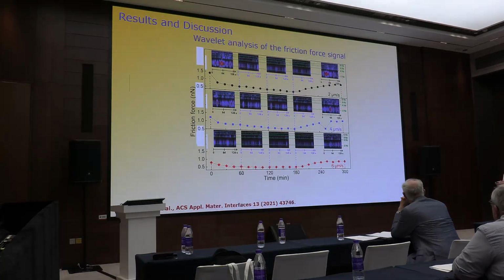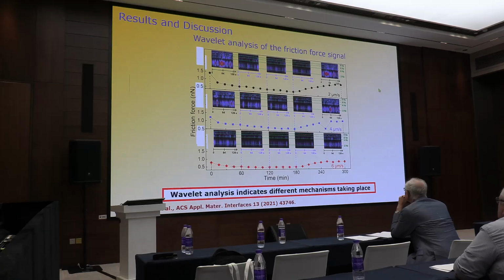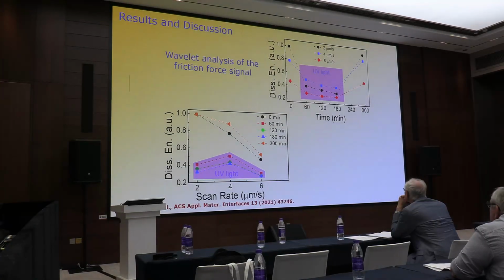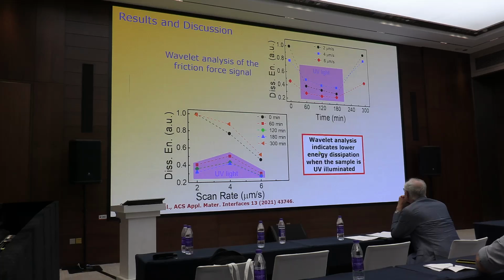Well, this is analysis of the AFM data. This is wavelet analysis developed by one colleague who analyzed the friction force. And what does it mean? The wavelet analysis indicates different mechanisms taking place in darkness or under UV light. The conclusion is that the wavelet analysis indicates lower energy dissipation when the sample is UV illuminated. The friction is reduced, so we have lower energy dissipation. This analysis is in agreement with the result of the tip.